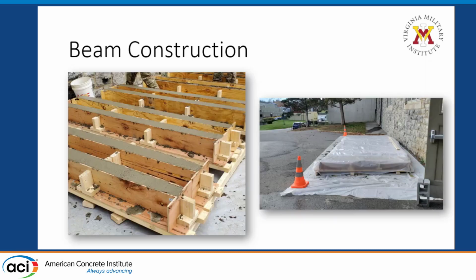All right, moving to beam construction. For the frames you see here, we used a 1/2 inch thick plywood and 2x4 sections to make the frames. We treated them with oil before we put in the normal concrete, and then the normal concrete was sourced from a local ready-mix company and delivered via a concrete truck.